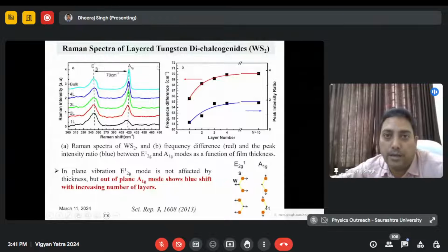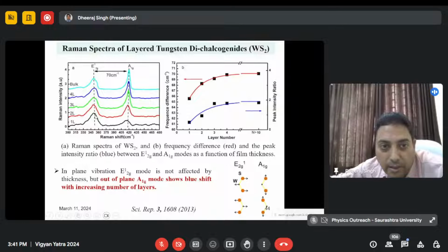Moreover, nowadays for 2D materials like WS2 or MoS2, Raman spectroscopy can clearly identify the number of layers. Suppose for a single layer, here is the Raman spectrum of WS2 thin films. For one layer, you can see that the intensity of the 345 peak is larger than the second peak. But when the number of layers increases from one layer to four layers, we can see that the intensity changes. Here the first intensity is now down, and the second peak at 420 cm inverse is greater. So the intensity variation gives a clear identification of the number of layers present at the nano level, where TEM will have some difficulty with this characterization. But Raman spectroscopy clearly identifies the number of layers in your 2D material by certain peak vibrations.